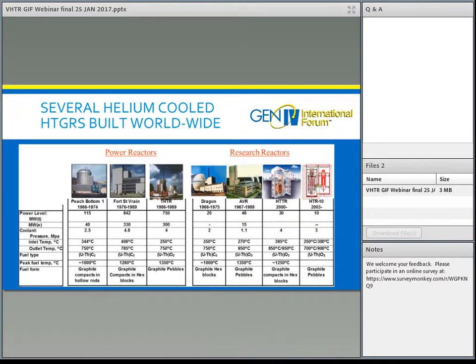So far as operating experience with helium-cooled high-temperature gas reactors, there have also been high-temperature gas reactors with carbon dioxide as a coolant. Some of the earliest reactor designs were of that type, the earliest commercial designs. In the area of power reactors, there was the Peach Bottom reactor and Fort St. Vrain reactor in the U.S. and the THTR in Germany. For each of these, it shows some of the operating characteristics, the coolant temperatures, types of fuel used, and the peak temperature in the core that it was operated at as compared to the coolant temperature. And then you see also how some of those used graphite compacts, which is what's used in a prismatic block reactor, or if they used graphite pebbles.